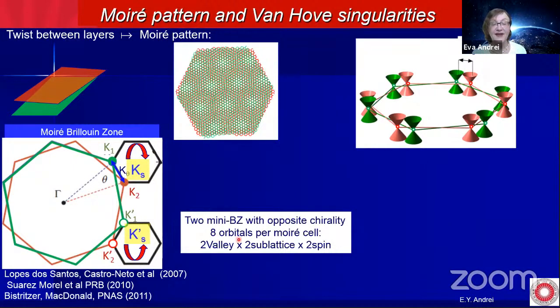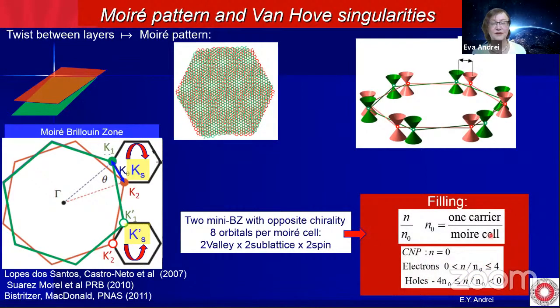and now we have 8 orbitals per Moiré cell. We have 2 for valley, 2 for sublattice, and 2 for spin. So in order to fill a band, you need 8 electrons to go into each Moiré cell. Let's call the filling of the band n over n naught, where n naught is 1 carrier per Moiré cell, and n runs from -4 to +4. So you have -4 for the hole sector and 0 to +4 for the electron sector.